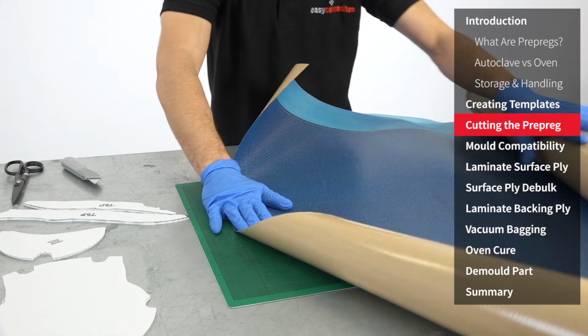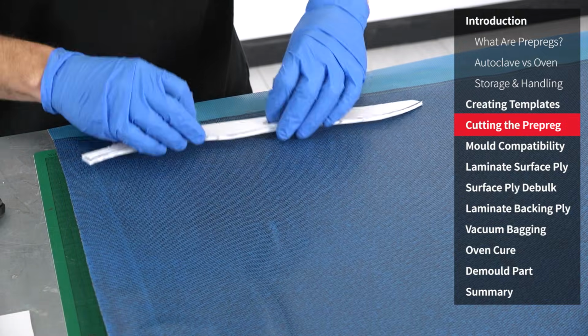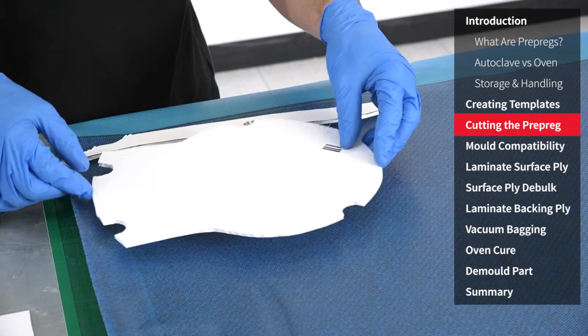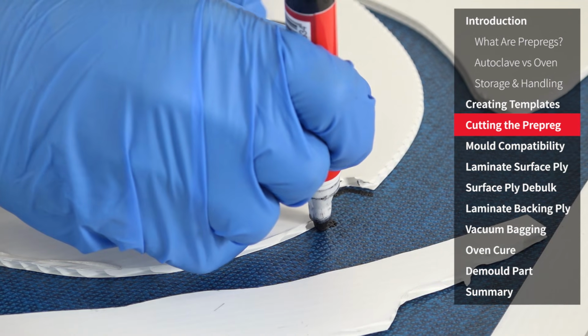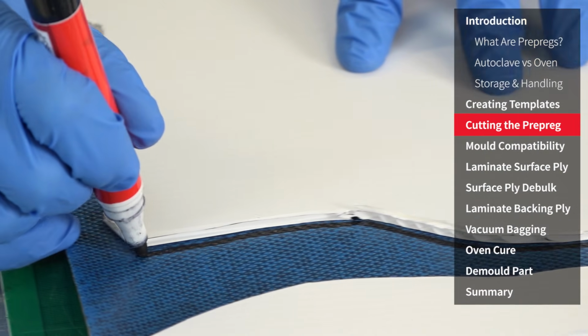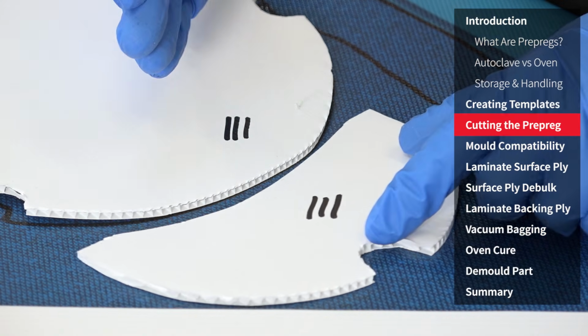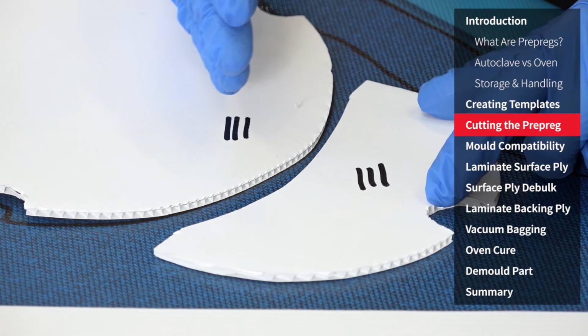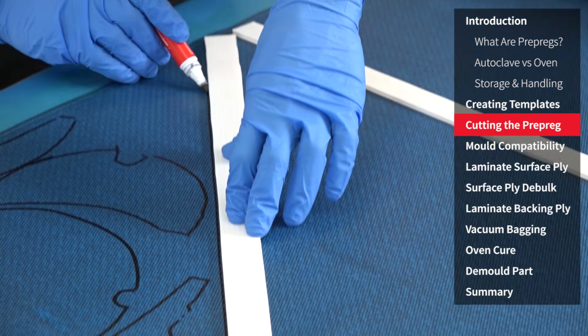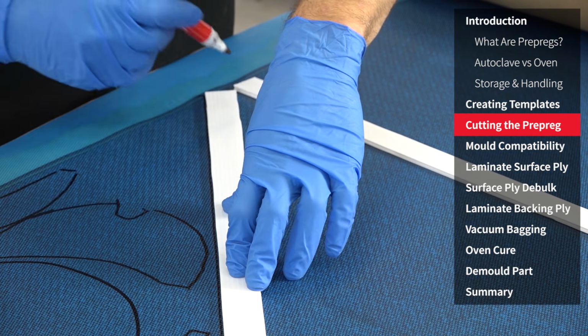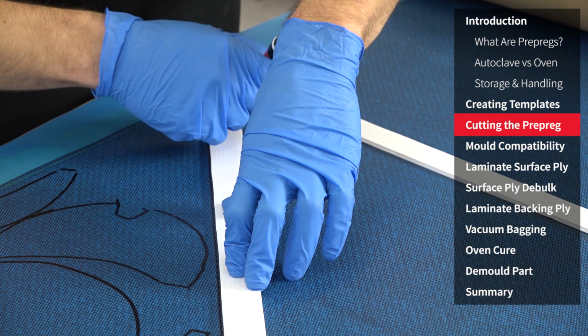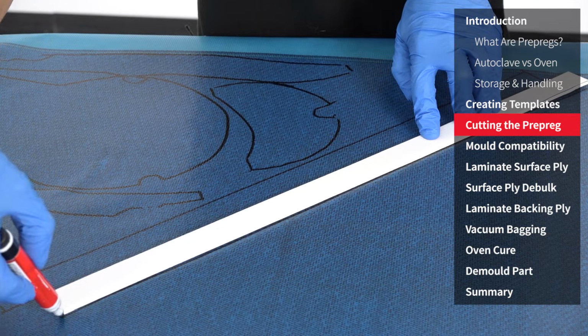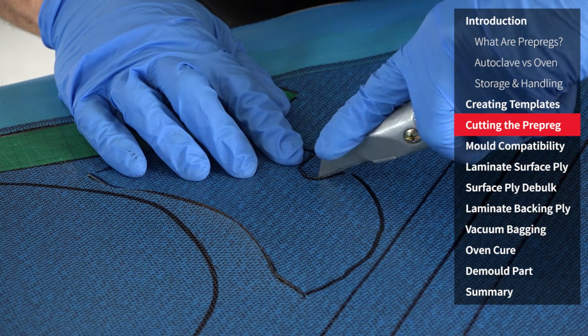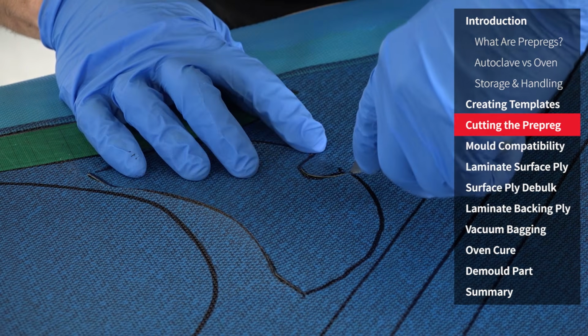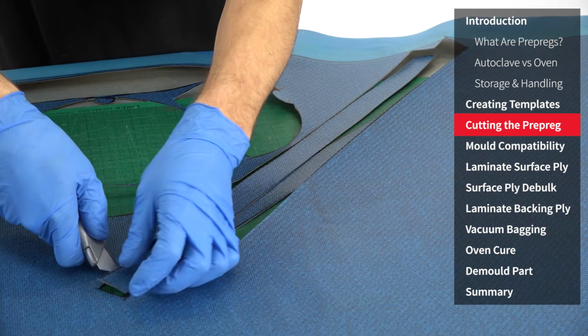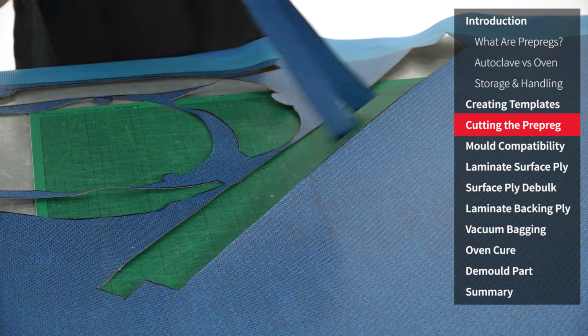One of the great advantages to working with pre-preg is how tightly and efficiently the material can be tessellated together, meaning that generally there is very little waste. When doing this, remember to pay attention to the fibre orientation and ensure that the components are aligned as needed. These strips cut at 45 degrees will be used around the rim of this component and will be cut to length on the job. You'll notice here that I'm using a knife for the cutting. Generally this is the quickest way, however, high quality shears will also cut the material very effectively.